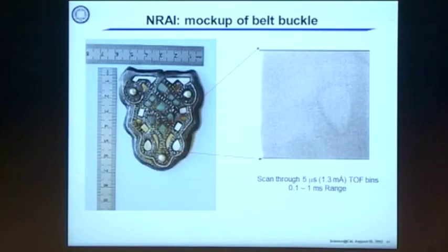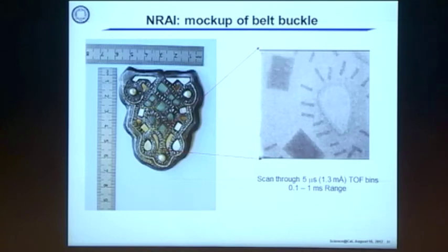Another thing I'll mention briefly is resonance absorption imaging. So far, I've been talking about neutrons of thermal and cold energies. But in a spallation source, or in a nuclear reactor, but for that we would need a spallation source, the neutrons are produced at all energies. If we use neutrons which are high in energy, electron volt type energies to a kilo electron volt, neutrons have very sharp absorption probability at certain energies. In that case, we can study different isotope distribution within materials.